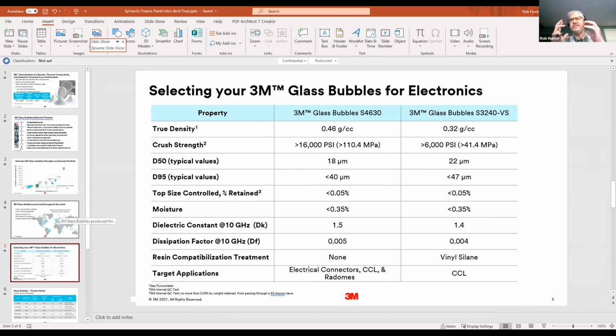So we either do gas phase pressurization testing with change in true density by gas pycnometer, calculating a volume percent loss. That's the way that we do it for lower strength products. For higher strength products like these, we use a liquid phase test where we have purpose-built custom equipment which exposes the sample dispersed in a liquid to 2 pressurization cycles with very delicate control of change in volume versus pressure. And so we're warranting what pressure 90% of the volume survives. So when we say greater than 16,000 PSI, we're saying, for instance, that for the new S4630, 90% of the volume of the spheres will survive 16,000 PSI in this test, or in this case, 6,000 PSI.